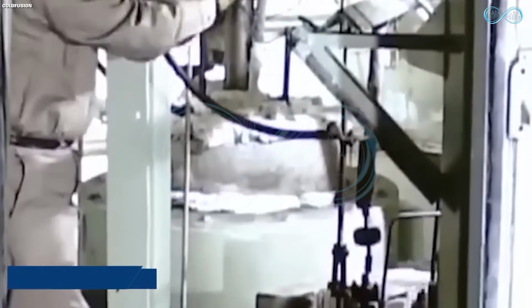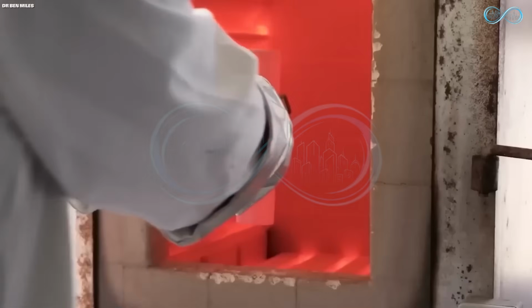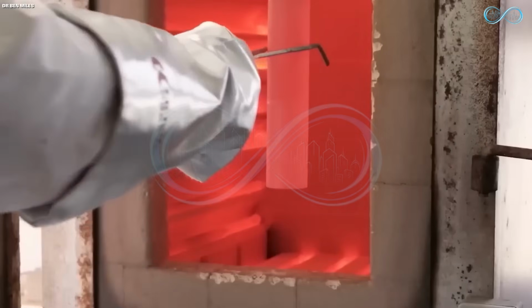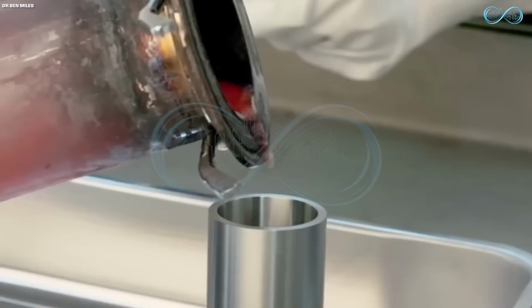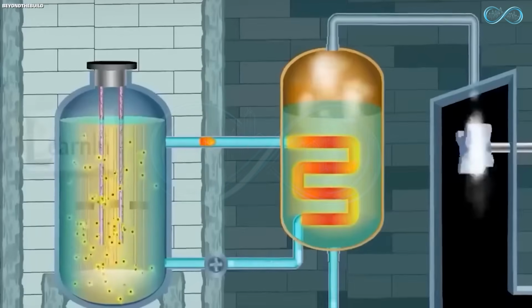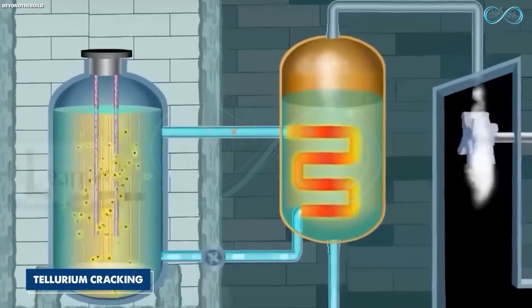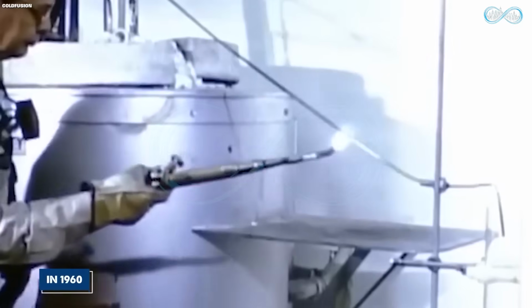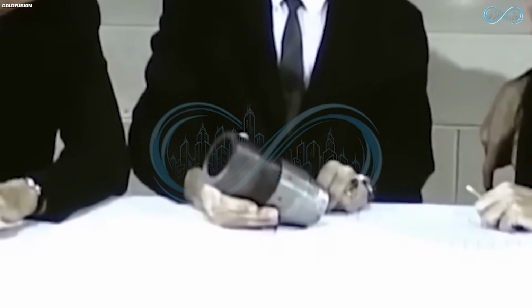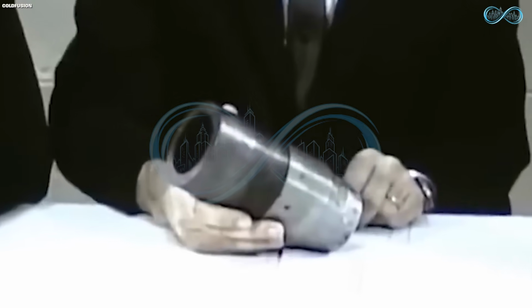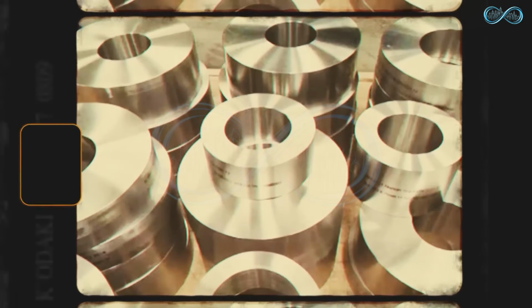That level of heat means they can penetrate microscopic grain boundaries in steel alloys, cause catastrophic embrittlement, and trigger a process called tellurium cracking that can shatter reactor walls from the inside out. In the 1960s, when Oak Ridge National Laboratory was running their experimental thorium reactor, they discovered that conventional stainless steel lasted about 6 months before the reactor vessel walls started to fail. Even the most advanced nickel-based superalloys of the era, Hastelloy, Inconel, and Haynes alloys, could only survive for about 4 years before they needed to be replaced.